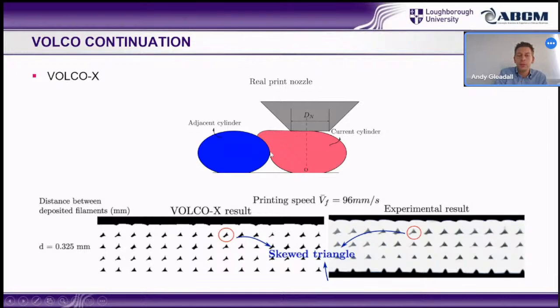So it analyzed at what point it was making contact with the previous filament and how at that point the deposition would change. So it was still very simple, but it could get these predictions for a different type of structure. I think there'd be lots of other versions that could be done for different types of structures and then potentially all brought together. And you can see the prediction of the microstructure is really nice. Even the asymmetry of these triangles is remarkably well predicted by the Volco model on the left compared to the experimental one on the right.